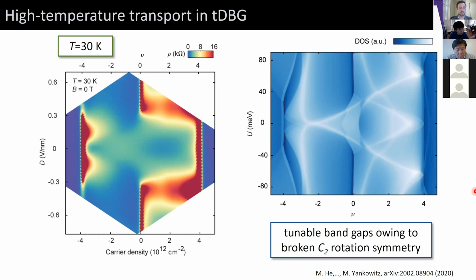Okay, so the first thing that we want to do is measure transport at slightly elevated temperature of 30 Kelvin, so that we suppress any possible correlation effects and just understand what we know from a single particle level. And when we do this, we find that actually this single particle model works pretty well. So the main features that we see are insulating states emerging at the charge neutral point, 0 carrier density at finite displacement field, insulating states at full filling, nu equals plus and minus 4, and then this cross-like feature, which resembles this cross-like movement of the Van Hove singularities within the flat valence band. Okay, so the general things that we understand about this system are pretty well understood from the single particle model.